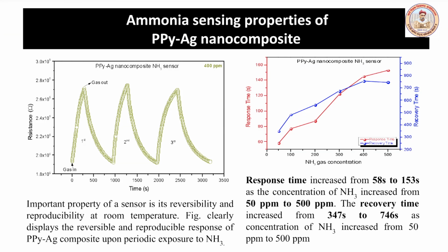The gas response values were observed to increase continuously with increasing gas concentration up to 500 ppm. The rate of increase of gas response is relatively higher up to 300 ppm, but response reduces between 400 to 500 ppm, leading to saturation. Important property of a sensor is its reversibility and reproducibility at room temperature. Figure displays the reversibility and reproducibility response of polypyrrole silver composite upon periodic exposure to ammonia. Response time increased from 58 seconds to 153 seconds as the concentration of ammonia increased from 50 ppm to 500 ppm. The recovery time increased from 347 seconds to 746 seconds as the concentration of ammonia increased from 50 ppm to 500 ppm. The testing is finished.